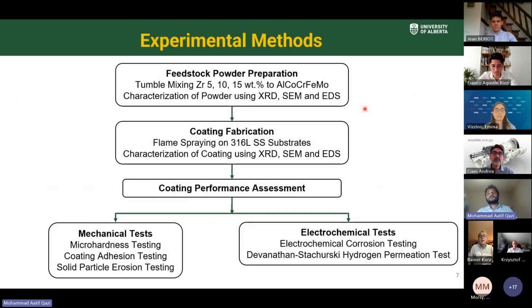The experimental methods include preparation of the feedstock by tumble mixing of Zr in 5, 10, and 15 weight percentage to AlCoCrFeMo, characterization of the powder. Then we move to the coating fabrication using flame spray on 316 stainless steel substrates, characterization of the coatings. Then the coating performance assessment using mechanical tests like micro hardness test, coating adhesion testing, solid particle erosion testing, and then the electrochemical tests like electrochemical corrosion testing, Devanathan-Stachurski hydrogen permeation testing.